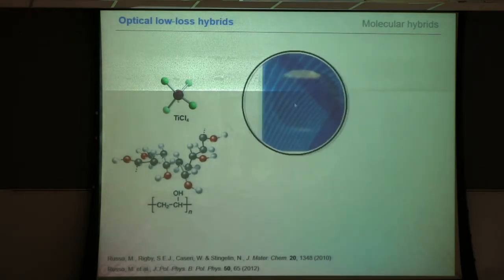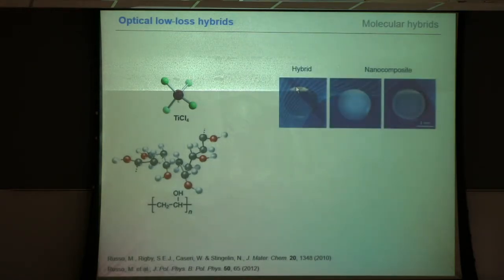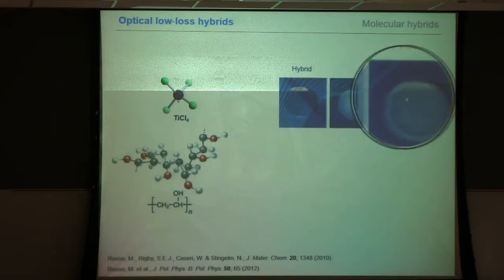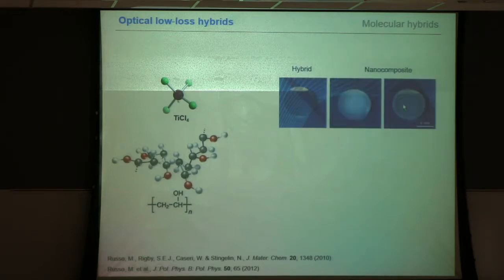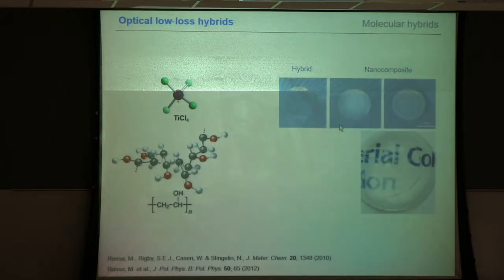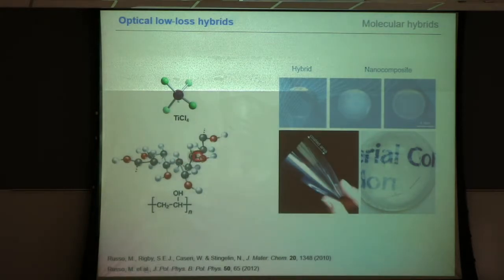It's beautiful and transparent. Very different to, for instance, composites where we just add nanoparticles into the film, where you immediately see the scattering effect. Even while titanium dioxide doesn't absorb, because of the aggregation of the nanoparticles, you get this unwanted loss because of scattering. And we can do that with thicker layers. So here we produce the lens. Clearly, mechanical properties still a problem, but that can be solved with higher molecular weight. And refractive index is obviously good.